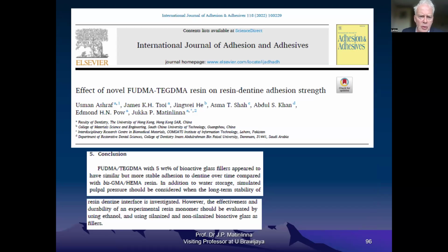Not so long ago, we published a couple of studies where we had a fluorinated urethane dimethacrylate molecule. This was with my colleagues in Hong Kong, in Guangzhou, China, and also my colleagues in Lahore, Pakistan, and Dammam in Saudi Arabia. And we found that fluorinated urethane dimethacrylate with 5% of bioactive glass fillers appeared to have similar but more stable adhesion to dentin over time, compared with the traditional or conventional resin.